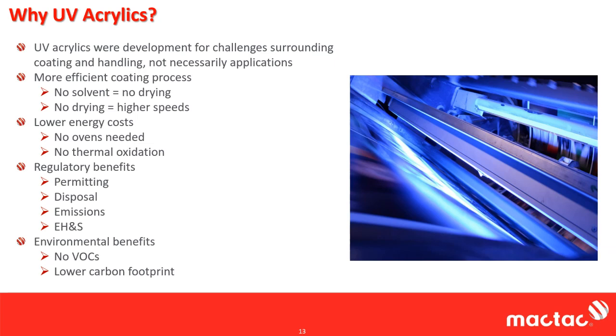Again, those ovens, they are burning a whole lot of natural gas in order to generate the heat needed to drive off the solvent carrier or solution carrier, solvent or emulsion. These ovens could be 60 to 80 some inches wide and 300 feet long in some cases. It's a lot of natural gas. And then you also have the thermal oxidation for the solvent-based adhesives, where EPA says you can't just blow solvents, VOCs, into the atmosphere. You've got to recover them or you've got to burn them off.